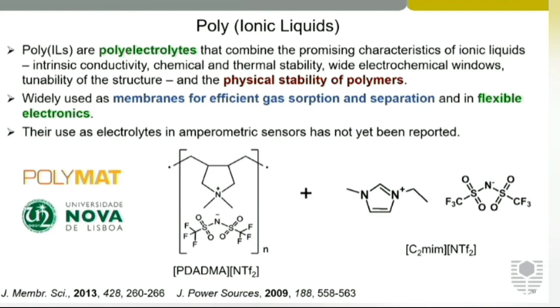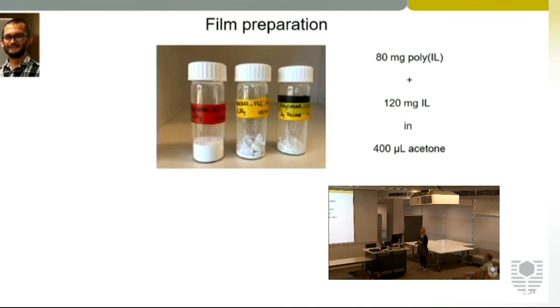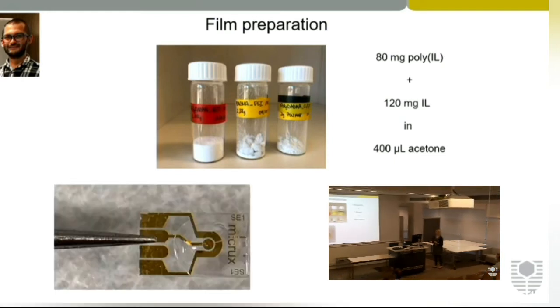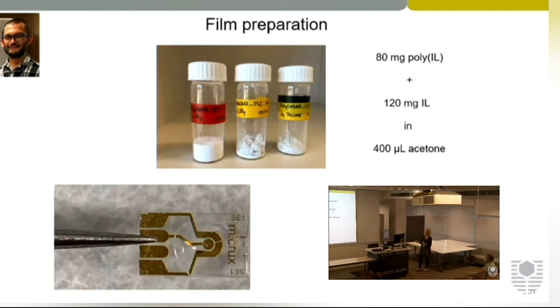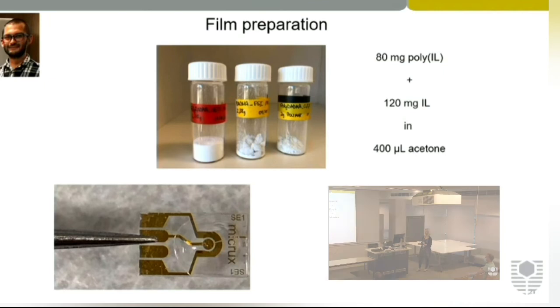What you can see here is, in this case, the cation is polymerized, so these are long chains, and then you have an anion that's freely mobile. And you have to combine them with an ionic liquid to create a membrane that we can use for electrochemistry, because the polyionic liquids are solids. So we use 80 milligrams with 120 milligrams of ionic liquid in a vial, and then add a fairly large volume of acetone as a mixing and transfer solvent. On our electrodes, this is a really large polymer film, just to show you what it looks like, but we don't normally use that much. Once the acetone is evaporated, you're left with this polymer film on the surface.